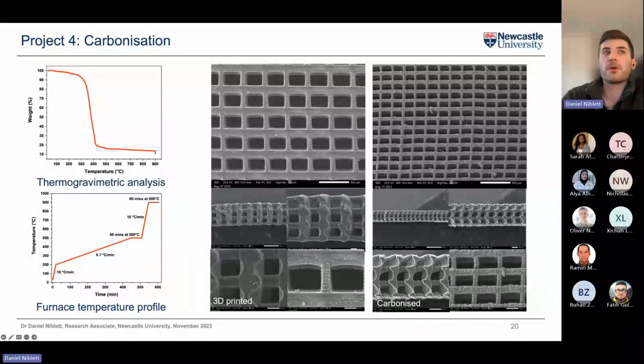So based on the thermogravimetric analysis, so that's the decomposition rate of the photopolymer that's printed, we can work out what's the furnace temperature profile, which is shown on the bottom left there, which will minimize the structural damage of these materials. So on the images, the column of images in the middle there, that is the 3D printed materials. And then the column of images on the right, that's the same materials but carbonized. And what happens is the material shrinks by about 50%. But as you can also see, a lot of the microstructural features are preserved during this process. So we're able to convert a photopolymer into a carbon microstructure, which then we can try and test.